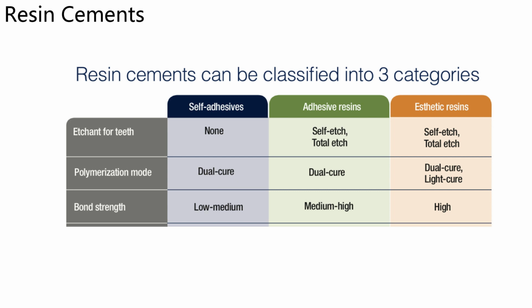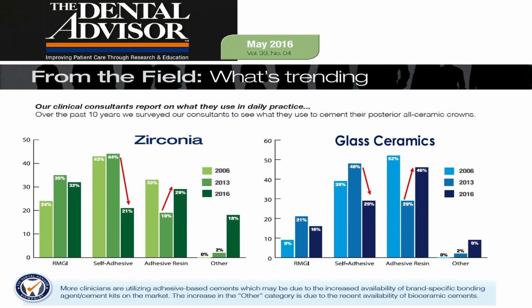Then we have the third category, which is also a type of adhesive resin cement. Basically, these are aesthetic resins, which are generally again used with etching techniques and are used specifically in aesthetic procedures like veneers and laminates. A clinical survey done in 2016 by Dental Advisor clearly shows that the use of self-adhesive resin cements is slowly coming down, as it takes a longer period for these self-adhesive resins to achieve optimal bond strength. So it has been seen that a lot of debondings are being observed with self-adhesive resin cements.